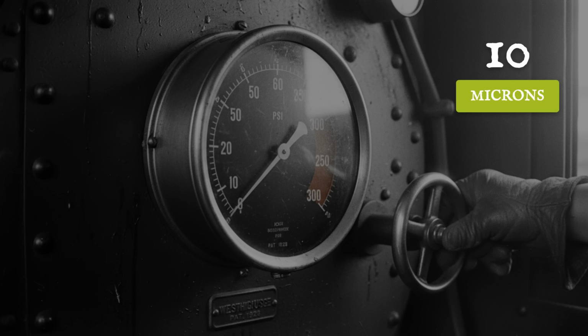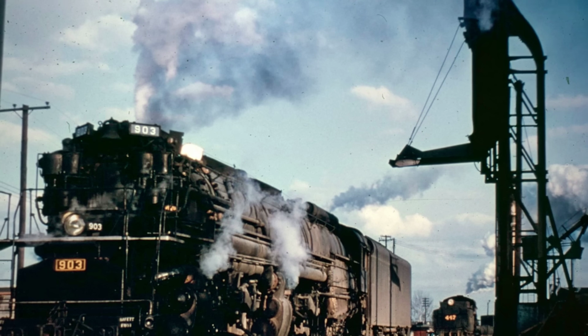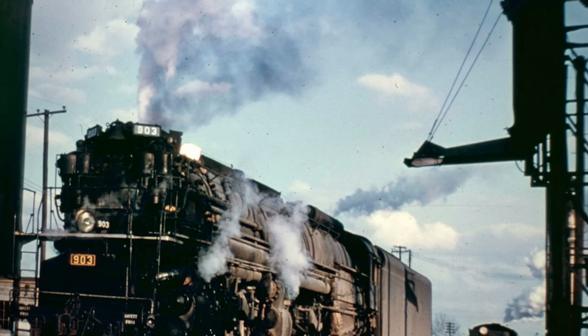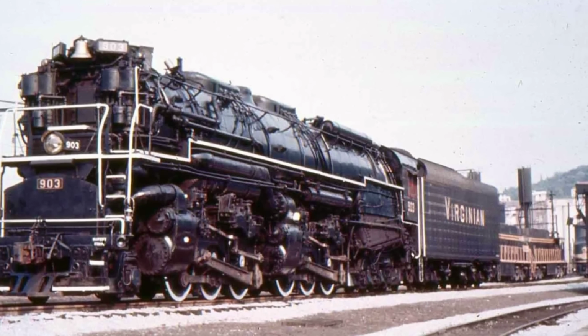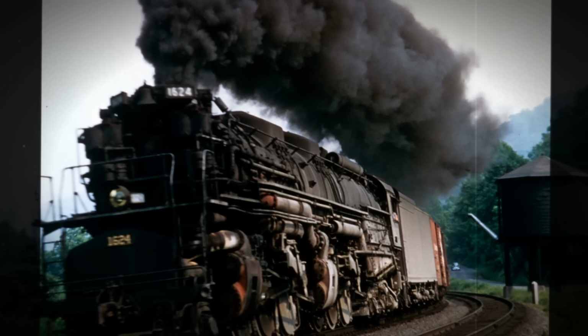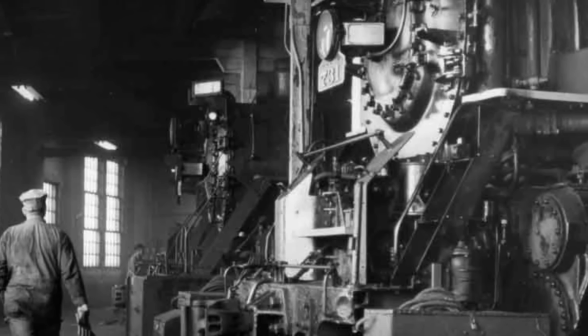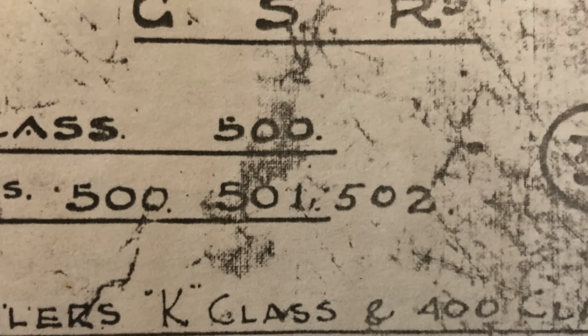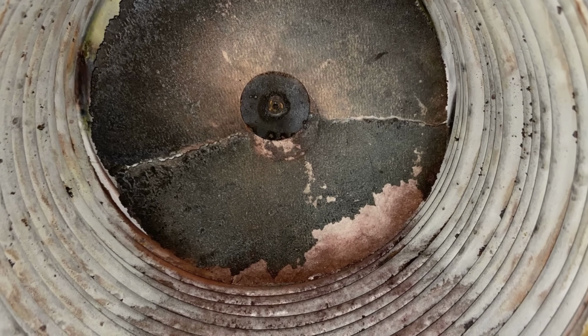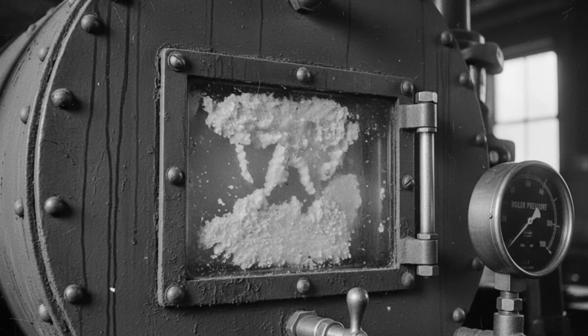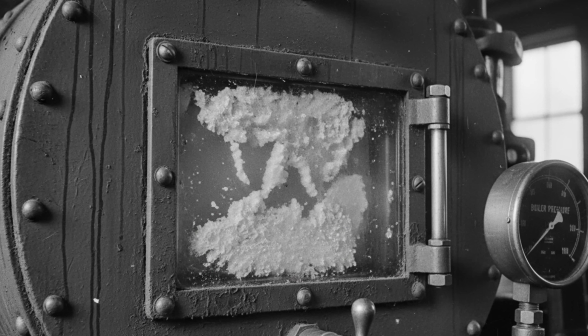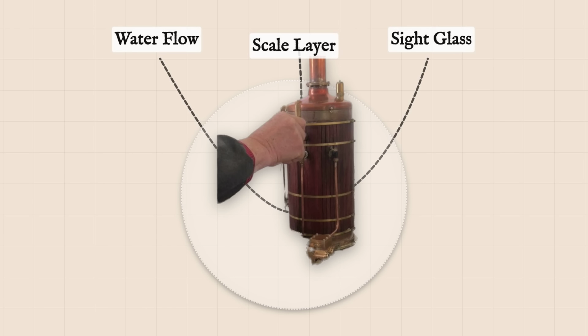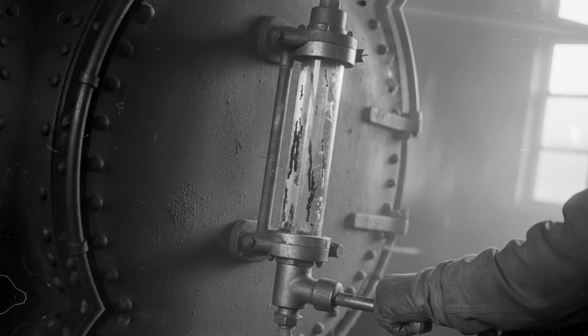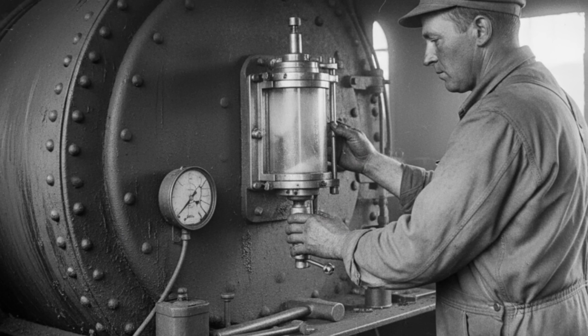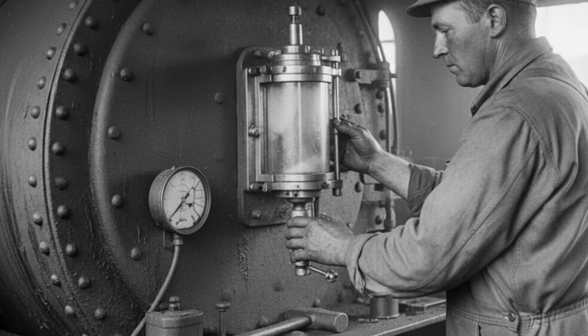At 300 pounds per square inch, the laws of fracture mechanics write the last line. A locomotive the size of the Allegheny is not just a machine. It is 600 tons of rolling steel, a mobile fortress built to haul mountains. But even a fortress can be brought down by the smallest oversight. In the Allegheny case, maintenance records show the sight glass was neglected for weeks. Calcium from hard water built up inside the glass, forming a white film that narrowed the passage to a pinhole. With each firing cycle, more scale layered the glass, clouding the operator's only window into the boiler's true condition.